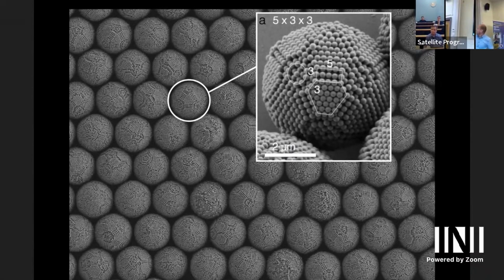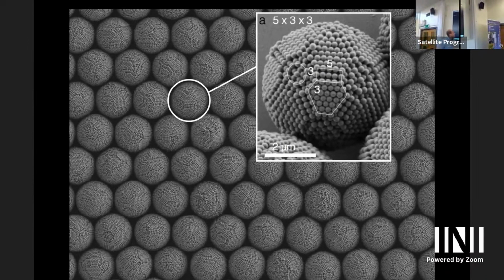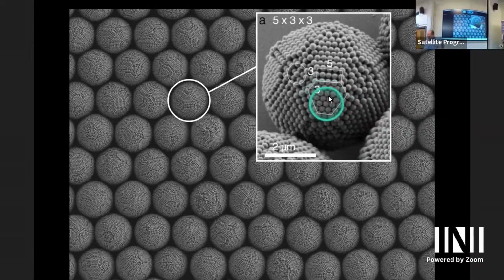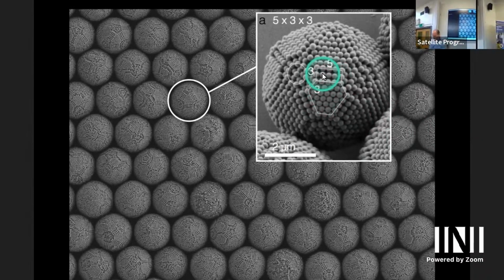And what you get here is essentially a polycrystalline cluster. There are 20 domains of FCC that are arranged with icosahedral symmetry in a symmetric fashion. And you also see on the surface these triangular domains and square domains. This is called the vertex region. This is the edge region. This is the face region.